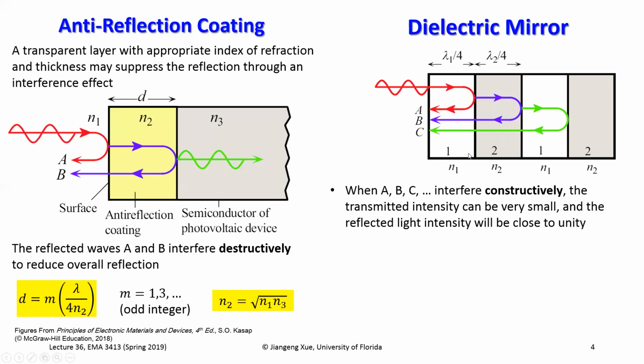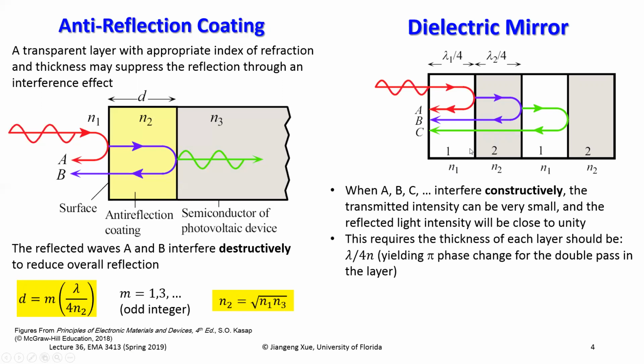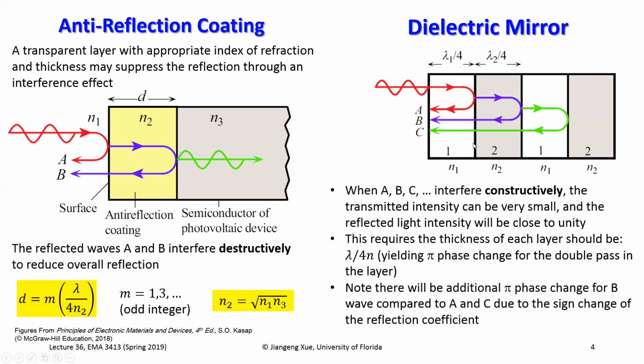So in this case, when we have these multi-layer stack, each of those layers have quarter wavelength thickness, then the additional light path in these material will be 180 degrees. However, considering that the light reflection of 1,2 interface versus 2,1 interface will have a reflection coefficient 180 degree off, there's a sign change that will give you additional pi phase shift that give you overall 2 pi phase shift for all those partial waves that allows the waves to constructively interfere, that give you almost unity reflectance in this situation.